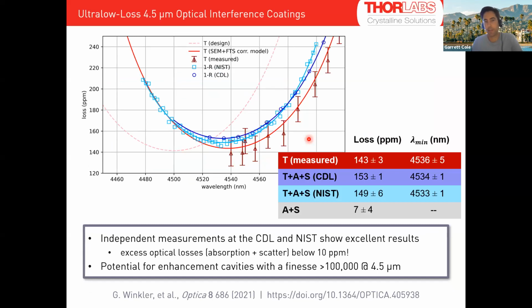I'm going to jump ahead and just show that in the last couple of years, we made some prototype optics at 4.5 microns. These were measured by some partners in Vienna and by some partners at NIST in Gaithersburg. These are extremely challenging measurements, to measure these ppm levels of loss. Here we push the transmission up in the optic to about 140 parts per million. We weren't sure what kind of excess losses we were going to get out here. We didn't want to be loss limited, but it turns out through careful measurements at the CDL in Vienna and at this group at NIST, we were able to tease out these very low levels of absorption, 7 parts per million.